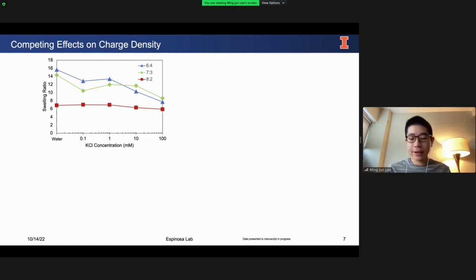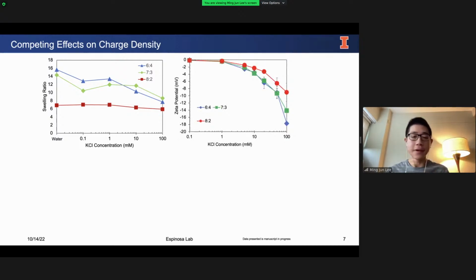And we see that for the hydrogels, I have 3 different recipes, the 6,4, 7,3, and 8,2. These are just the molar ratios of the copolymer. But in general, as the salt concentration increases, the swelling ratio of all these hydrogels is decreasing. At the same time, the zeta potential, a measure of the surface charge of my hydrogels, is also getting stronger and stronger. It's more negative as the salt concentration increases.